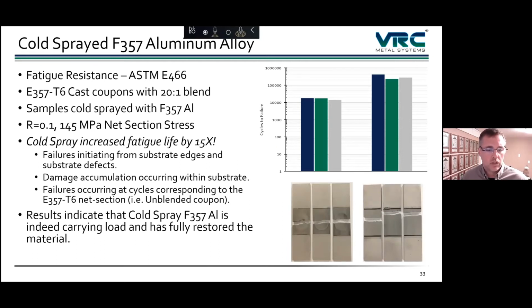It's a little unconventional from a specimen design standpoint. In this case, we're taking a flat panel that's got a blend out in it, and we're repairing the blend area to try to get increased performance over a blended region. The idea here is that blend outs are already approved by the Navy. This is for NavAir. Blend outs are already approved by the Navy. So if we can get improved properties over a blended coupon, we don't even have to get back to a pristine coupon, but we can just get better properties and we can have success.